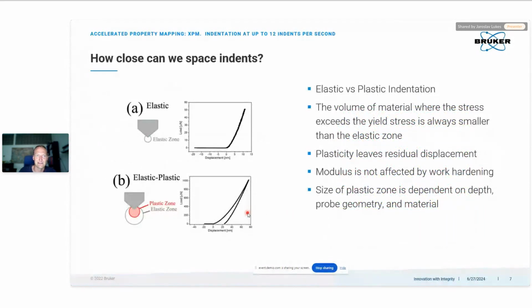The most basic question that I usually get is how close we can get the indents together, and what is basically the resolution of such a map. Right. I must say, you have to think about what the output is and what you are interested in. If you are interested only in the elastic properties, you have more freedom. If you're interested in the absolute values of the hardness, then it's a different story. Let me just remind you: if you do a very shallow indent in the elastic regime, the load and unload will go along the same line. You create an elastic zone under the indenter, and if you unload, there is no residual indent, there is no residual deformation.